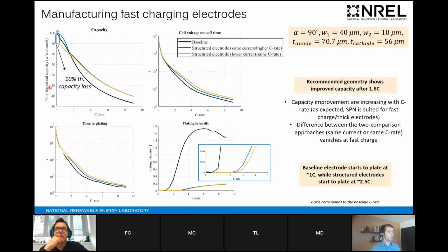In this graph, for example, we've got percent of theoretical capacity. You can see at low C rates on the x-axis, we have less capacity because we have removed material. But as we go to higher C rates, like a C rate of about 1.6 or so, we start to see benefits of the laser ablation channels. In particular, we're looking at 6C, that's where our interests are, charging in 10 minutes. We see about a 25% increase in the theoretical capacity that can be achieved in a 6C constant current, constant voltage, 15 minute charge protocol. We also see benefits in the cell voltage cutoff time, and we see major benefits in the reduction in lithium plating. This is the plating intensity. We go from a plating intensity of about 1.7 down to less than 0.2 for a 6C rate.